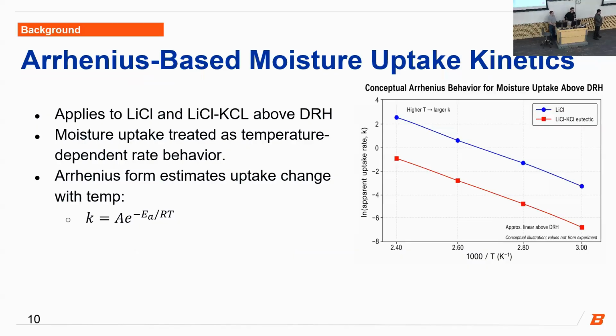To round out the background section, we used an Arrhenius-based model to describe moisture uptake as a temperature-dependent process for our lithium chloride and eutectic salts above their deliquescence relative humidity. Like Scott said, once the salts are above their DRH, they transition to bulk diffusion rather than just surface adsorption. The main idea is that high temperature will increase the uptake rate, allowing accelerated testing to predict lower temperature performance. We are doing this because lithium chloride and the eutectic have lower DRHs than 20% relative humidity, which is the lowest humidity level that the chamber can go.